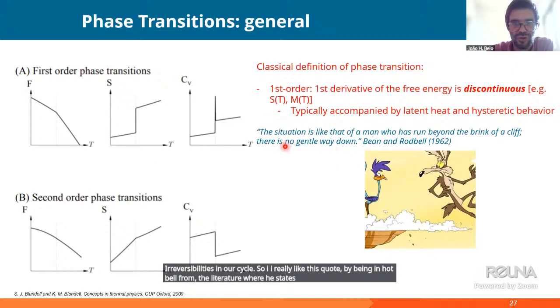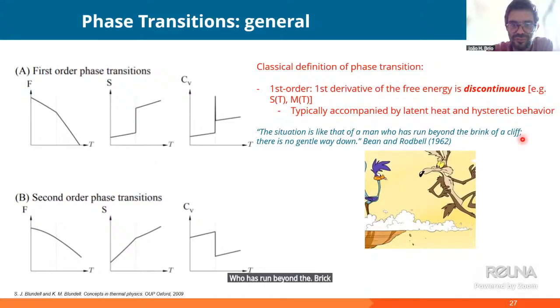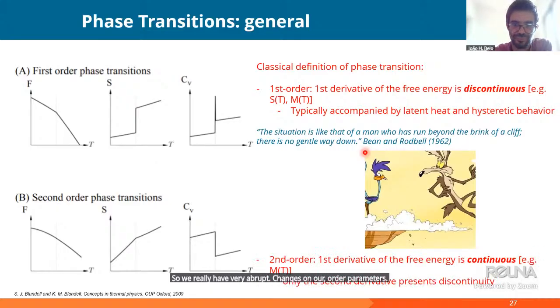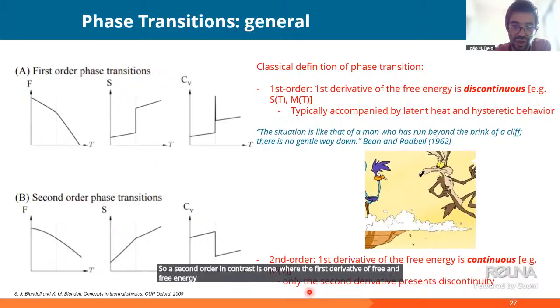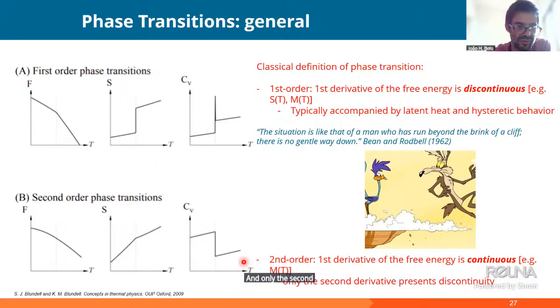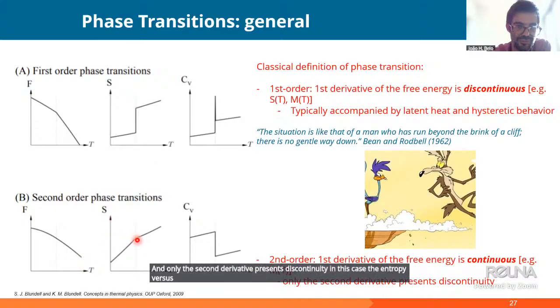So I really like this quote by Bean and Rodbell from the literature, where he states that for first-order phase transitions, the situation is like that of a man who has run beyond the brink of a cliff, so there is no gentle way down. So we really have very abrupt changes in our order parameters. A second order, in contrast, is one where the first derivative of free energy is continuous, and only the second derivative presents discontinuity. In this case, the entropy versus temperature, as we can see here.